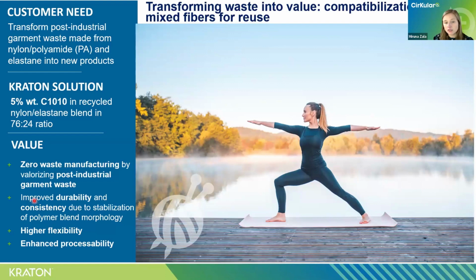So here we have a case study where the customer was looking to reuse their post-industrial waste of mixed nylon and elastane blend in a ratio of 76 to 24%. The answer to this challenge was our solution, Circular Plus C1010 at a low loading level of 5% in this blend. Our solution enabled zero waste recycling by allowing the complete reuse of post-industrial waste, while enhancing material stability to ensure durability and consistency in the final product.